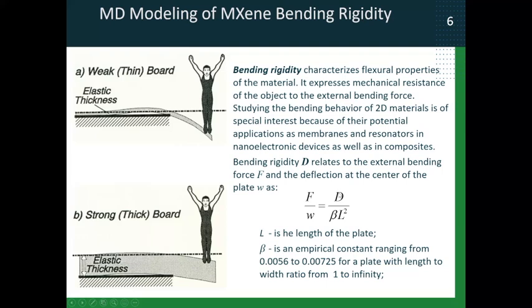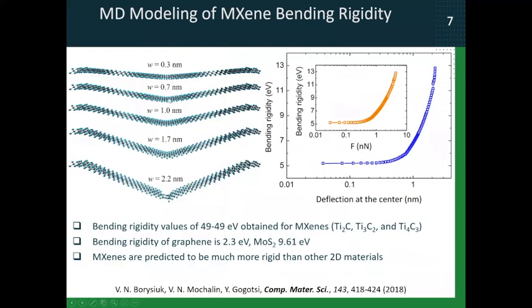And this is how we have done it from molecular dynamics, because again, we can measure force, which is required to deform MXene as shown here to a certain extent. So this is the extent of deformation, 0.3, 0.7, 1, and you see we bend it more and more. And of course, we need more and more force as shown on these graphs. And then from these graphs, you can determine bending rigidity. So we have done it.